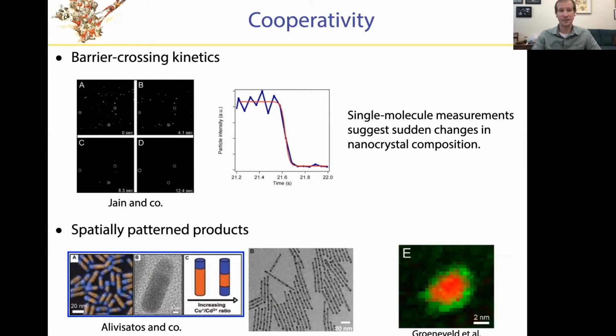These are amazing single molecule measurements where they can monitor the progress of this ion exchange over time for individual nanocrystals. And what they see is that an individual nanocrystal doesn't gradually trade one kind of ion for another. Instead, in this case, this nanocrystal waited around for 20 seconds, not much was happening, and suddenly, in a fraction of a second, its composition changed completely. Right? So this is not a gradual one by one process, but instead something that's highly collective, a sudden change in the nanocrystal's composition.